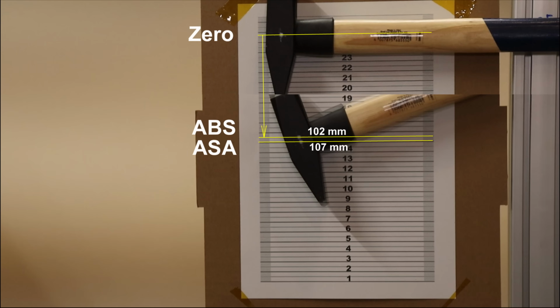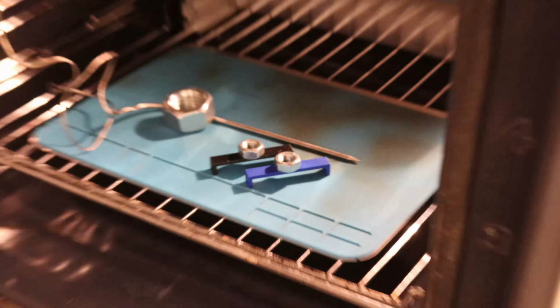The temperature test in the oven, where I want to record the temperature of the first deformation. This is a sped up video. It's a little bit hard to follow the numbers, but in both cases they start to deform at approximately 94 degrees Celsius, which is typical for these materials. I will start the experiment at 110 degrees Celsius.